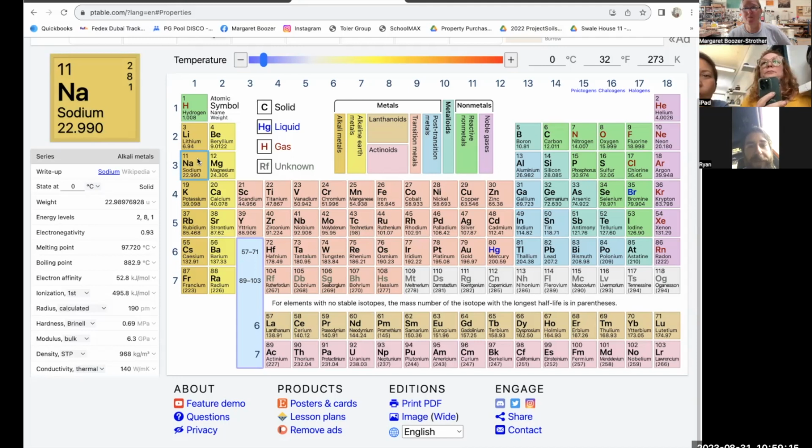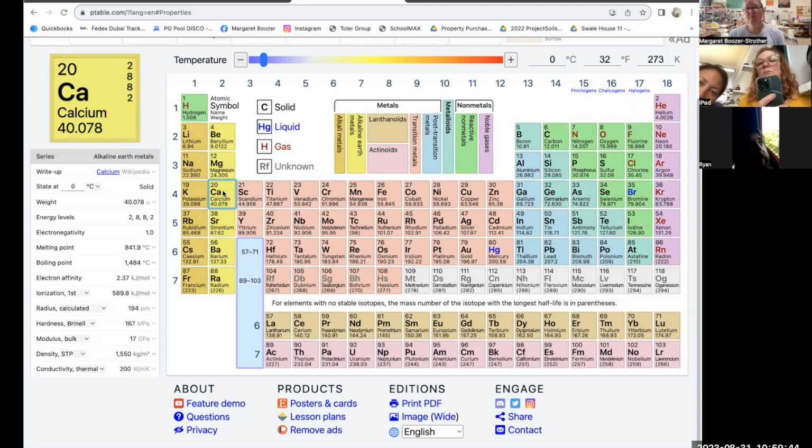to the right. That's magnesium, calcium, strontium, and barium. The most common one is calcium, which is why I said just dump in some whiting to make that glaze a little bit more durable. But also, these yellow fluxes here, the alkaline earth fluxes, they affect the way that our colorants work. And calcium is most likely what's already in the Albany slip. So using calcium won't affect the way that your colors work, as opposed to magnesium, strontium, and barium, which might change your colorants a little bit.